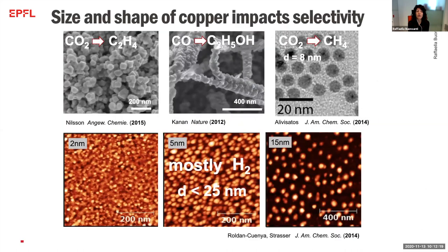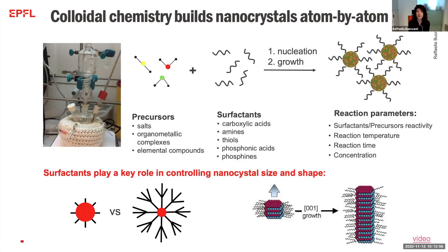So when I started my group, researchers around the world had already started to see that by changing the size and shape of copper, you could get some impact on the selectivity. At the same time, there were also some contradictions. For example, some groups found that copper spheres were producing methane, while other groups found that copper spheres actually produce hydrogen, so are basically not selective for the CO2 reduction. So at this point, we decided we could contribute with our knowledge in the formation of nanocrystals to the field.